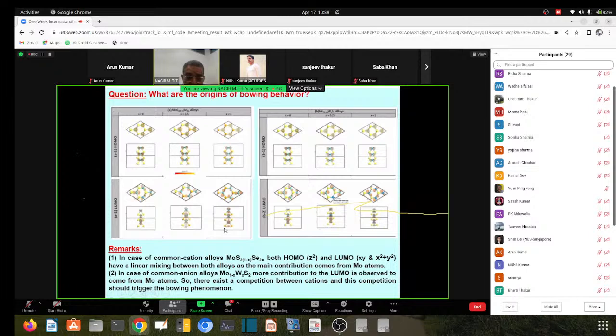In the first case, we have only one metal, so basically the contribution is from molybdenum. But in the second case, where you have two metals, tungsten and molybdenum, you can see there are contributions from two atoms. Mainly molybdenum: at the top you have molybdenum in blue color, and something turning to green, between green and blue. Whereas the dark blue is the tungsten. But when you have x equal to 0.25, the tungsten is depleted and does not contribute to the conduction band edge wave function. So it means there is competition between the tungsten and the molybdenum.